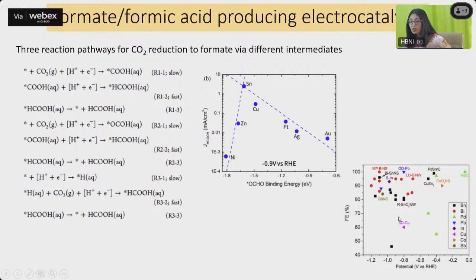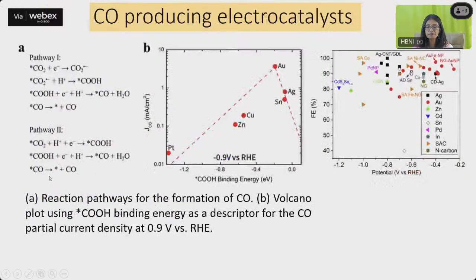Here, this was the volcano plot for these metal surfaces, whereas over here you see these different kinds of tin-based materials which have been used. FE, what was it? Faradaic efficiency. So you see the Faradaic efficiency of processes wherever tin has been used. They are quite high. And if you look at the potential, it is also quite achievable. So that is why tin-based catalysts are good electrocatalysts for the formation of formate or formic acid from carbon dioxide.